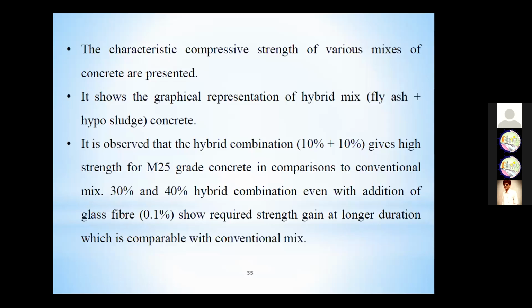Now, the characteristic compressive strength of various mixes of concrete are presented. It shows the graphical representation of hybrid mix, fly ash plus hypo sludge concrete. It is observed that the hybrid combination 10% plus 10% gives the high strength for M25 grade concrete in comparison to conventional mixes. The 30 and 40% hybrid mix combination, even with the addition of glass fiber 0.1%, shows the required strength gain at a longer duration, which is comparable with a conventional mix. So 30%, 40% we definitely can use, but the duration is large, and that's the problem regarding the time period. We go up to 360 days also.